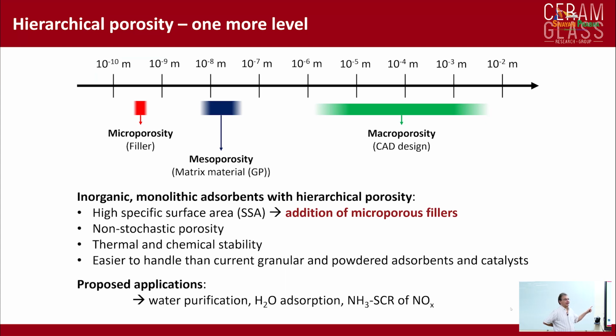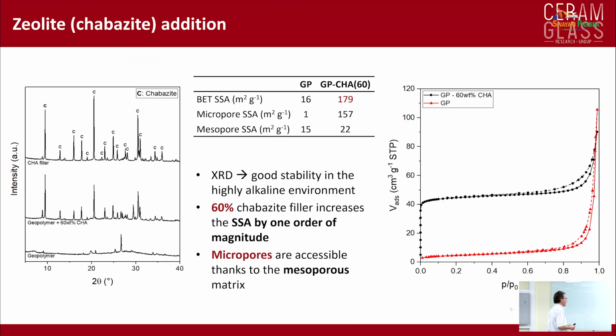And I would like to point out that we can do that and it works because the geopolymer matrix contains 40% of mesoporosity. And this leads to a wide volume of interconnected porosity that allows access to the fillers with the microporosity. If we had a dense matrix, of course, this approach wouldn't make sense, but we have a permeable matrix. So we tested for some applications. As you might have gathered, we work mainly on shaping and manufacturing of components rather than testing them. So we need to collaborate with people that have these capabilities.